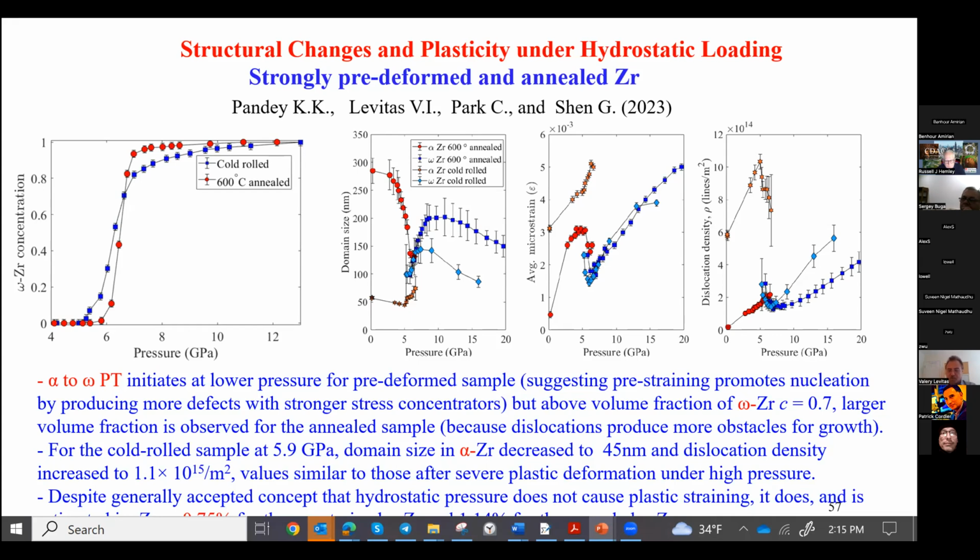Yes, actually, this is what is planned in our current project from the Metal program. We already have a tool, the dynamic rotational diamond anvil cell, which allows rotation up to 4,000 rotations per minute. Then the question will be how fast in situ measurements can be produced. I am absolutely sure that strain rate will affect the sequence of phase transitions, and of course it may affect the mechanism of plastic deformation, and amorphization will be observed more often. The relative effect of time scales, the typical time scales for plasticity, for phase transition, and for various structural changes, this interplay will be important and will determine all phenomena.